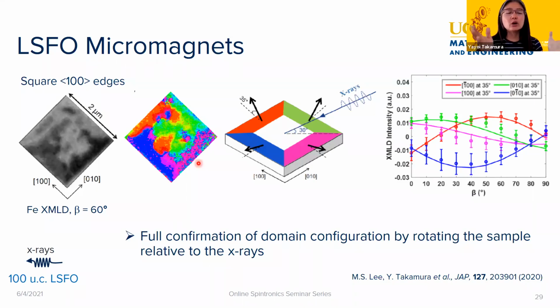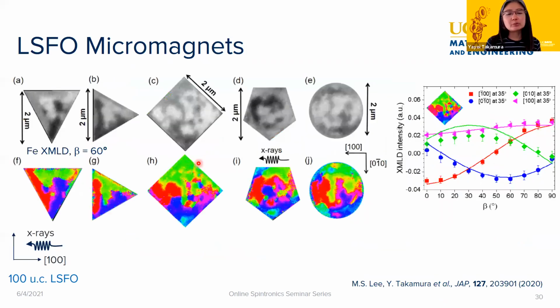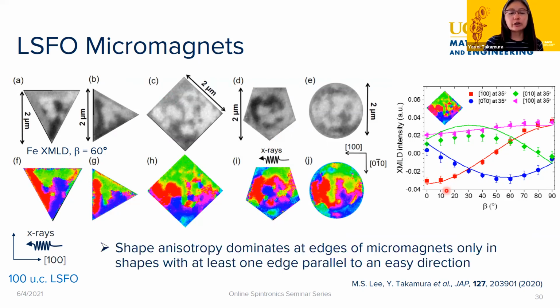Okay, so this is now for when the edges of the nanostructures were along the 1, 0, 0 directions, which are the easy axes for the antiferromagnetic spins. And then we tried a whole bunch of different shapes. Now we have different shapes, where many of the axes are not along these easy axes. And so we had this series of different types of domains. Again, we can bin them. I won't show you all these curves for all different shapes, but we could do this binning for all of them to characterize where the locations are.